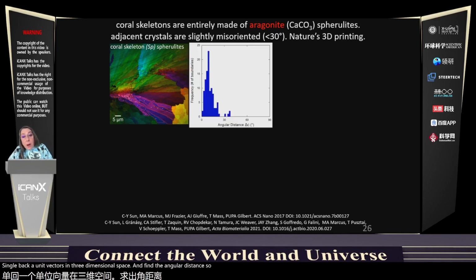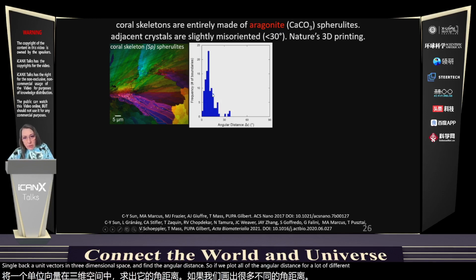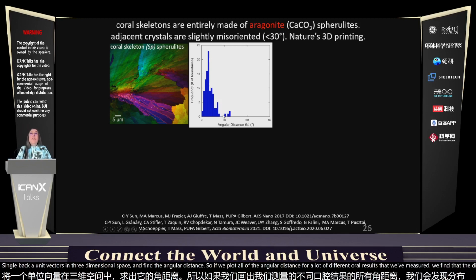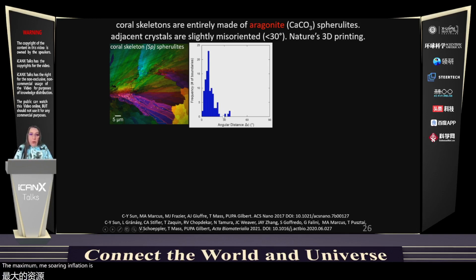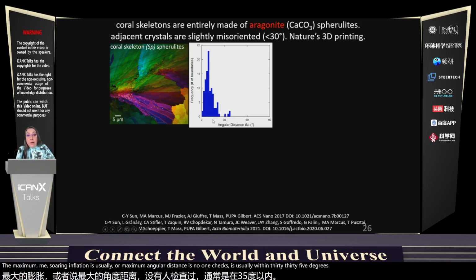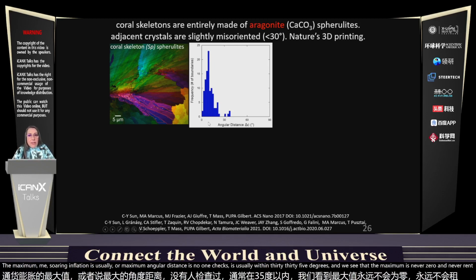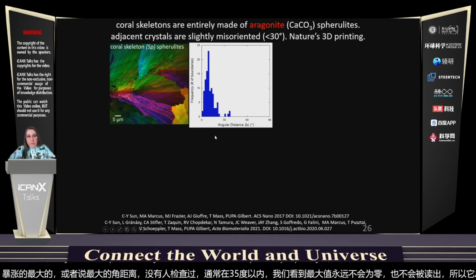So if we plot all of the angular distances for a lot of different coral crystals that we've measured, we find that the distribution is very narrow. The maximum misorientation, or maximum angular distance in three dimensions, is usually within 30-35 degrees. And we see that the distribution is never at zero and it's never random. It's always a narrow distribution with a small number, like 5 or 10 or 15 degrees, something like that.